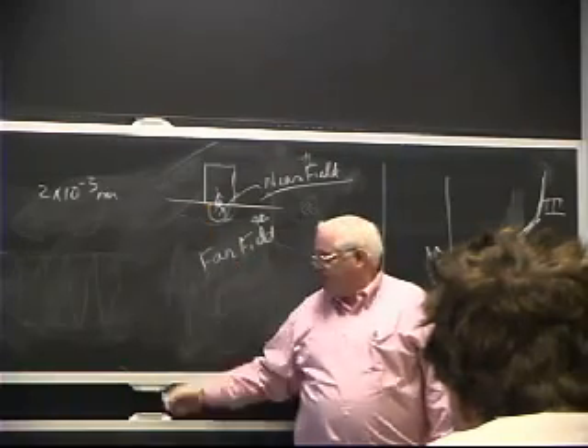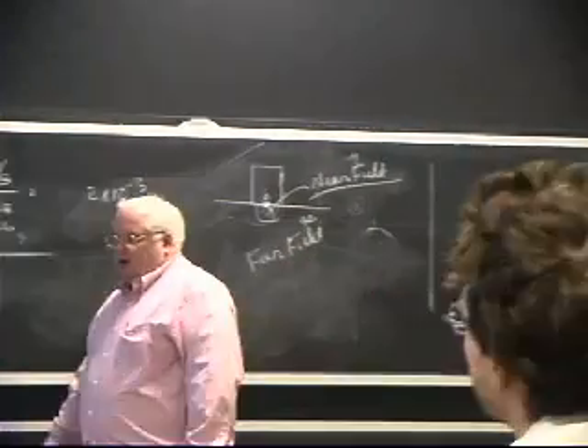So generally ultrasonics is for thicker plate rather than thin plate. Ultrasonics is fantastic and can measure things. If you're just trying to measure the thickness of something, they have little $500 or $1,000 ultrasonic gauges, so that if you've got pipes, like they just ran the pipe over there for the gas, and it's been in service for 30 years, and you want to know how thick the pipe is, or you've got a boiler and you want to know how thick the boiler wall is after all the corrosion, you can go in there and you can measure the wall thickness within 1/1000th of an inch.